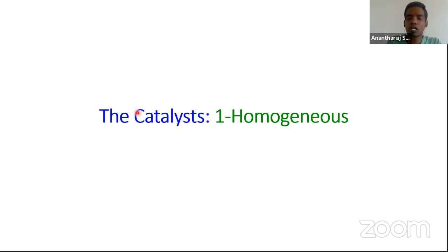In the case of homogeneous catalysis, we disperse the catalyst in the same medium where the reactants are present, which means that in conventional electrocatalysis or water electrolysis, whatever I have been telling you so far, everything is done with 2 electrodes, which are heterogeneous electrode surfaces, and those are the electrocatalyst. And in the case of homogeneous water electrolysis, what people do is they design an electrocatalyst which can be homogeneously dispersed into the solution, I mean the neutral waters, and you choose inert electrodes which do not have any catalytic property for both water oxidation and water reduction, and you apply the desired potential for the process. So this is homogeneous water splitting, and we have a few interesting electrocatalysts which I am going to talk about.